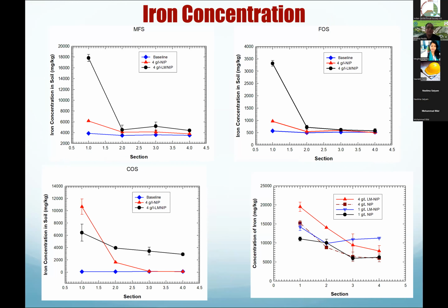And we can measure the concentrations at the end. After you've done the test, you can take out the sample and cut it into sections, and then you can see how much iron is retained in the soil. And of course, you can analyze the effluent, how much is coming out, but a lot of this iron could be trapped in the sand. That's fine. We don't have to worry about that much. But the whole idea was we want to be able to have iron throughout the sand.